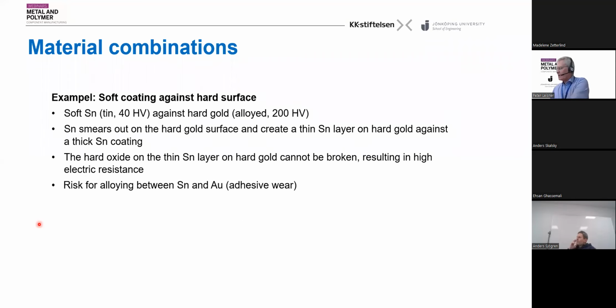So another example of material combination is where you have a soft coating against a relatively hard coating. And in this example here, we will have tin, which is very soft, 40 Vickers, against hard gold. And hard gold is gold which is alloyed to be harder, in this case 200 Vickers. And if these two are in contact, the tin will smear out on the hard gold surface, creating a very thin layer on the hard gold.